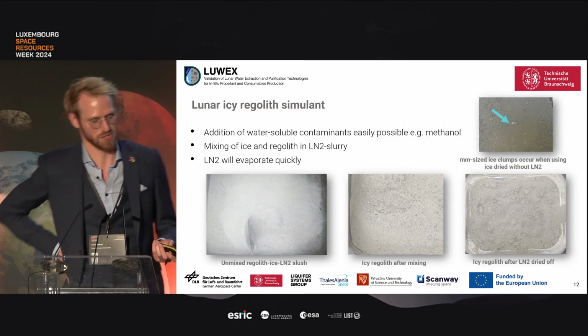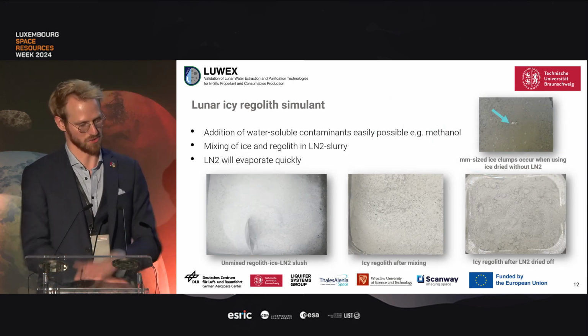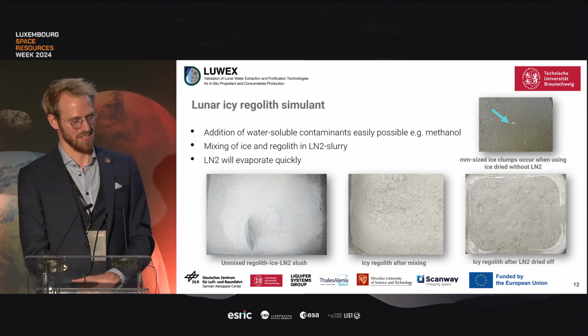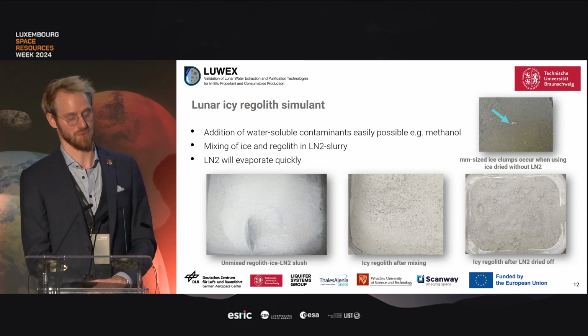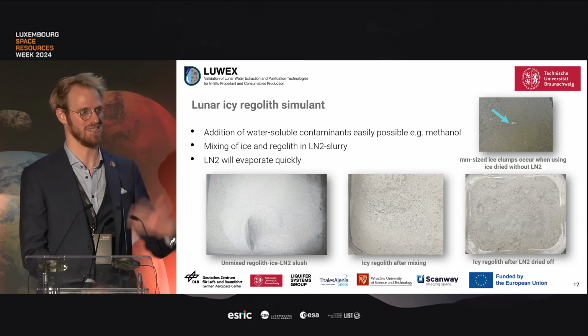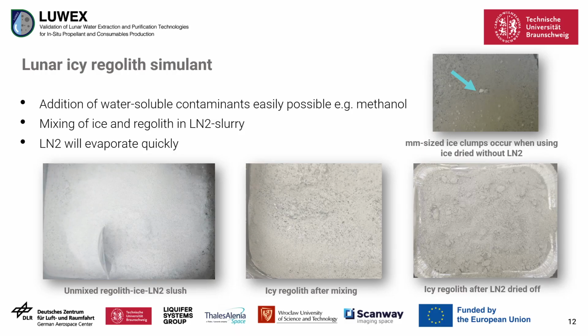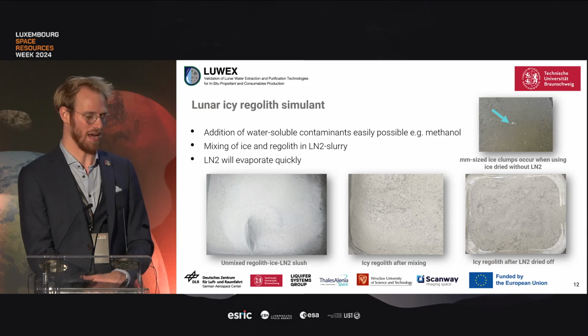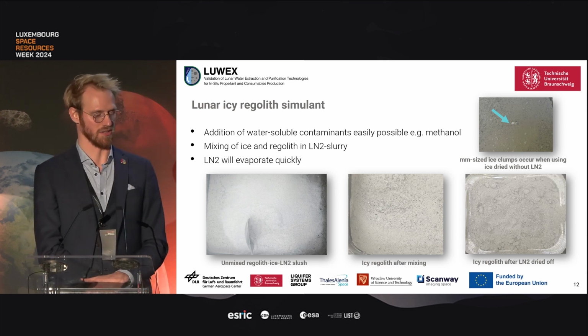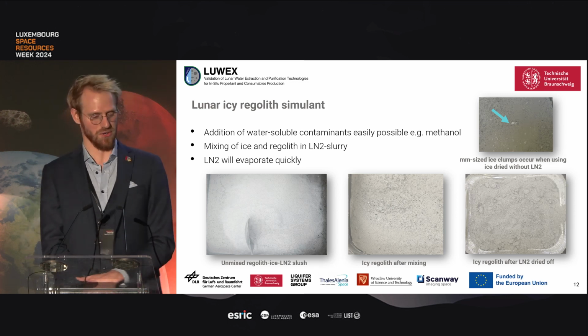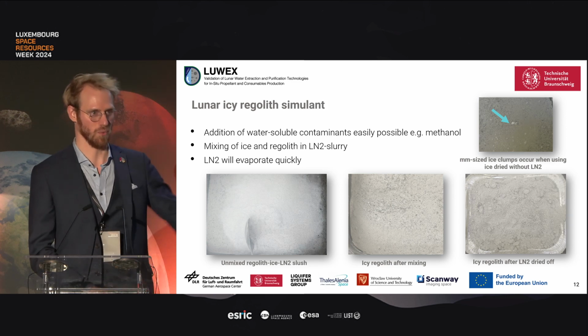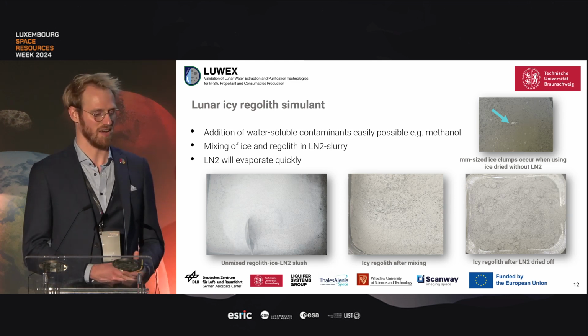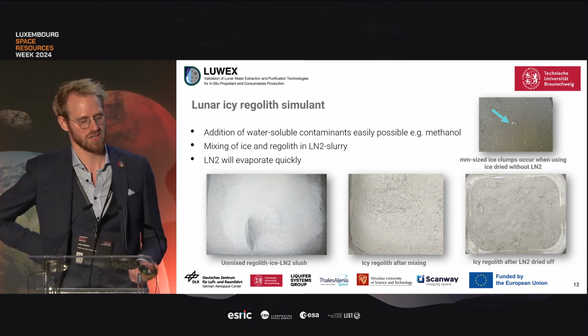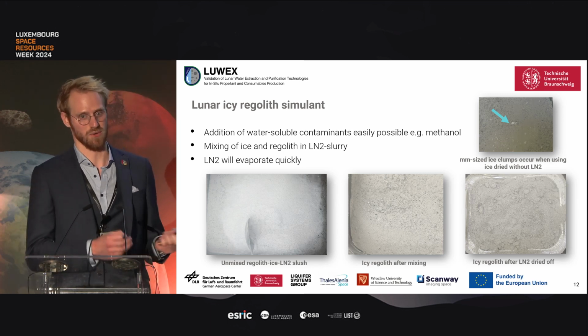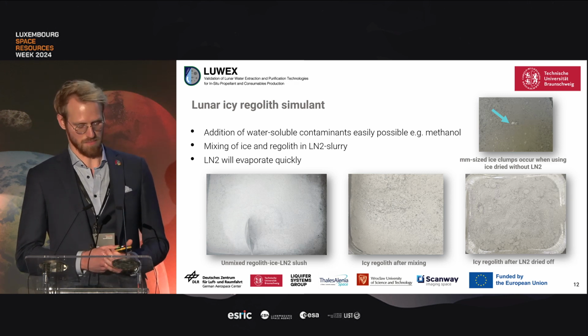Here are some photos of this process. On the bottom are the photos of how we mix this. As you can see, they are a bit fuzzy, and that's because we use a lot of liquid nitrogen, and that keeps evaporating as we go. So it's a bit gassy there. Yes, and then we also add the other volatiles during that process. If we do not use a lot of liquid nitrogen here, so if we try to cool down the sample first, then add the ice, we found that we create large ice clumps, and that we do not want. We want to make use of these incredibly small ice particles.